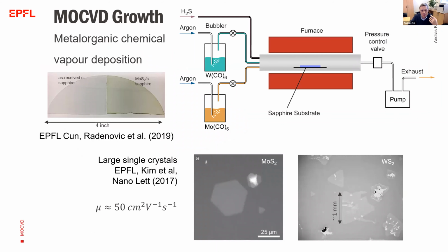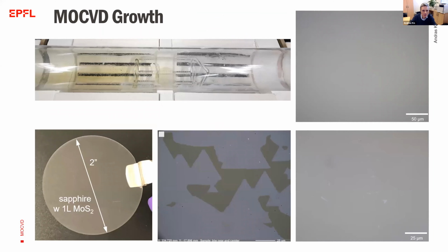So the first approach was to use, instead of exfoliated material, MOCVD grown material based on the chemical reaction between carbonyls and H2S, where in principle you can grow very large grain size, high quality semiconducting 2D materials. In principle, you can also do this on a wafer scale. So we have been able to do that for quite some time now.